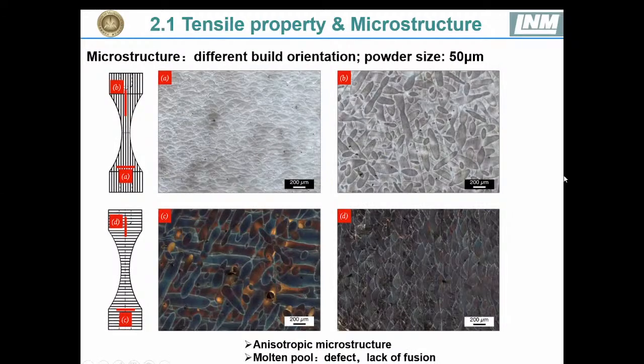Due to this anisotropic microstructure, the microstructure is observed by optical microscopy from 2 different orientations. Here we can see from this direction a fish scale pattern, which is typically generated by SLM due to this thermal gradient. And in figure B, we can see that there are some molten pools. We can see that sometimes they are not continuous. This is because the laser can sometimes penetrate different layers and make them connect with each other.